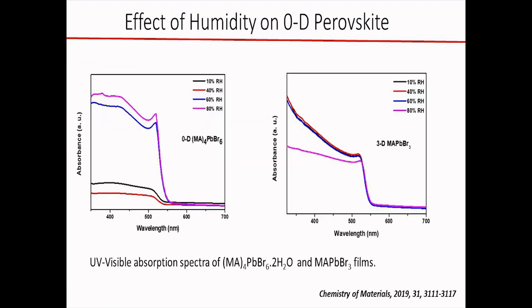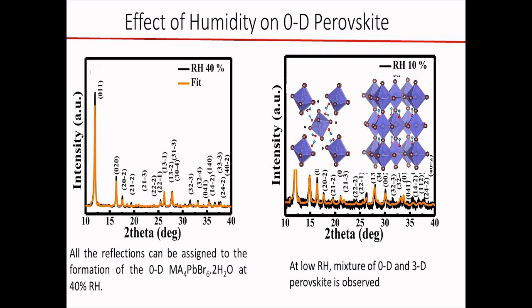We see the same thing in the UV-Vis spectra when you take the spectra. At 40% RH, the film is completely transparent and we don't see any absorption coming up. But when the humidity is higher, we see visible light absorption coming up from the methyl ammonium bromide films.